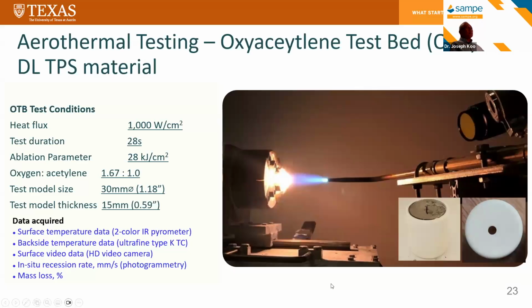Okay, this is another slide I'm going to share with you, where we apply this OTB to a dual-layer TPS material. These are the OTB test conditions. We use a Gardon gauge and measure the heat flux, and we have heat flux versus axial location from the OTB. We use the heat flux and the test duration, and the product of those is used to calculate the ablation parameter.